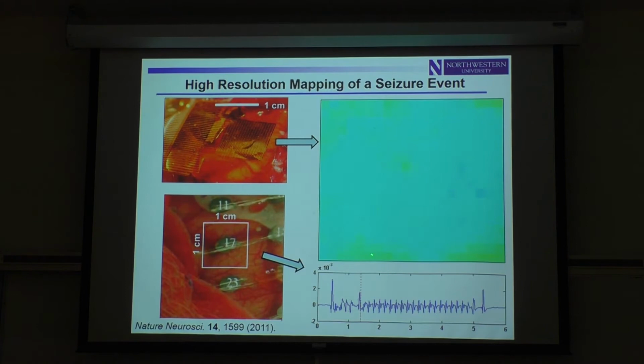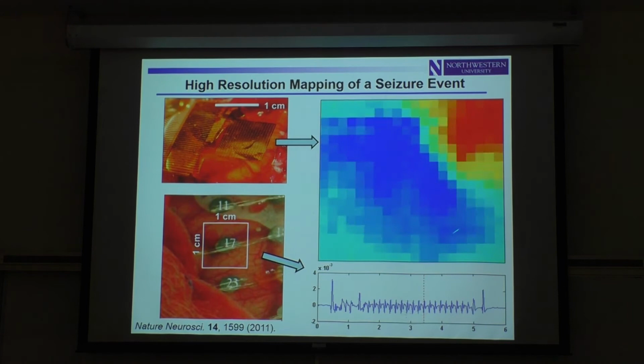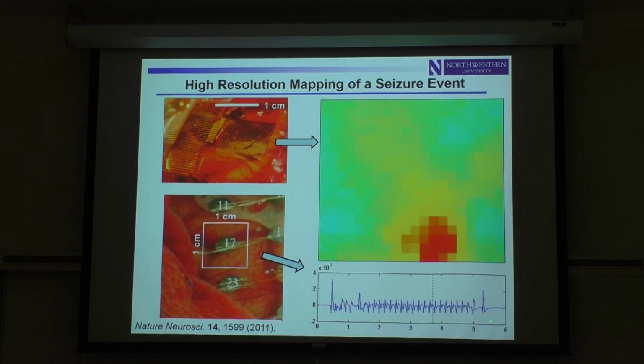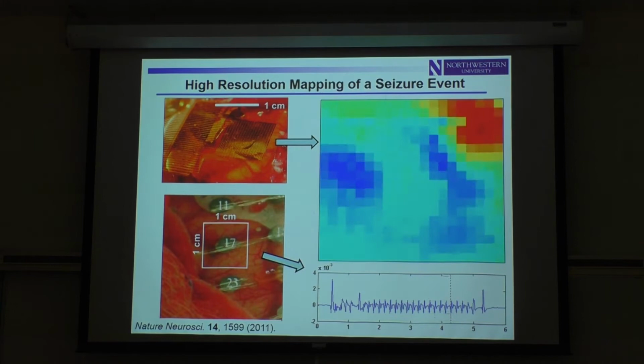The actual physical seizure doesn't set in until about a second and a half later, corresponding to this repeated sort of periodic trace in this individual channel, reflected in this recurring spiral wave instability that you see moving around in this way. From the clinical utility standpoint, you can use these maps to identify the anomalous region of the brain for extraction. From a research tool standpoint, this provides new information on the basic physiology of epilepsy, because what this shows in this particular case is a remarkably repetitive electrical signature associated with the seizure, and then magically it just annihilates itself and disappears, for reasons that nobody understands, about 5.5 seconds later. And so this tool enables insights that weren't possible previously, just due to the kind of spatial and temporal resolution that's possible.